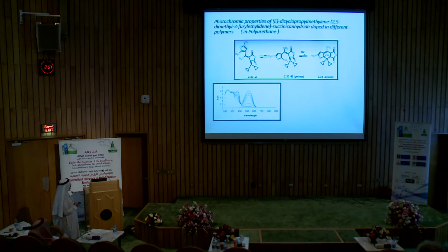This is the UV spectrum, or the photochromic performance, of the polyurethane polymer doped with a suitable amount of this fulgide. We can see that in the beginning, the absorption is only in the UV region, and then by increasing the irradiation time, there is development of a new band at 500 nanometers. This band is responsible for the formation of the color, the closed form of the reaction. This can also be reverted back completely to the E form, which is colorless, by taking off the source of the UV light or irradiating with white light. So this is the photochromic behavior which happens if we have glass coated with this polyurethane coating.